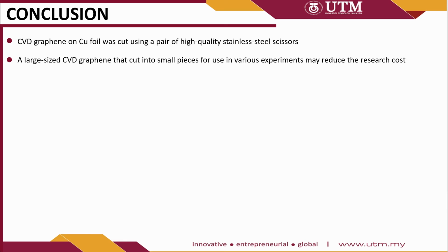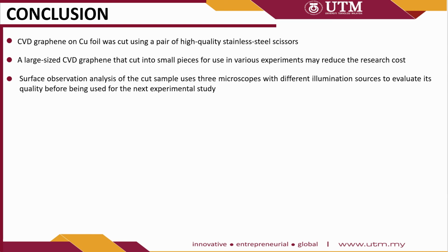As a conclusion, in this study, CVD graphene on copper foil was cut using a pair of high-quality stainless steel scissors. A large-size CVD graphene that is cut into small pieces for use in various experiments may reduce the research costs. Surface observation analysis of the cut sample used 3 microscopes with different illumination sources to evaluate its quality before being used for the next experimental study.